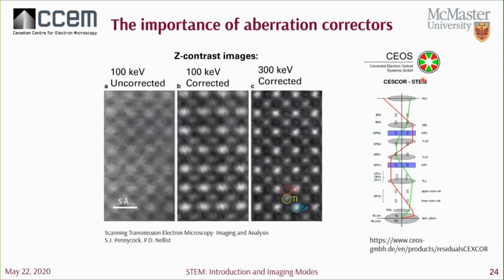While it's still possible to obtain atomic images without correctors, we can see the benefits of aberration correction. With a smaller probe formed from the correctors, you can see that the contrast is brighter in the image as compared to the uncorrected image. Correctors also provide an advantage in that they form a brighter probe due to the fact that the probe is smaller. This means that we can increase scattering in our sample and therefore increase the signal that we collect, giving us a better signal to noise ratio.